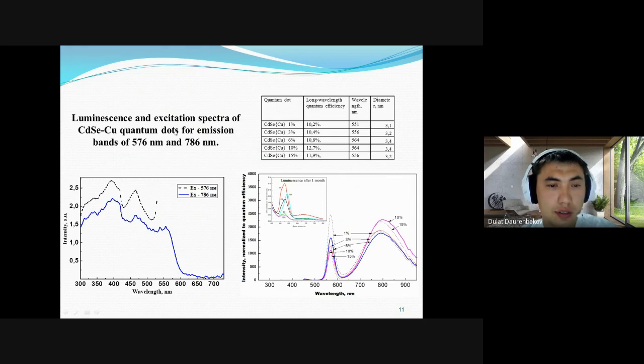Here we study the excitation spectra of cadmium selenide copper quantum dots. As you can see, the impurity luminescence and the host luminescence, the matrix intrinsic luminescence, have the same excitation spectra. By that, we can say that impurities are introduced inside the host, and this is direct excitation, and the host gives the energy transfer from the host to the impurities.